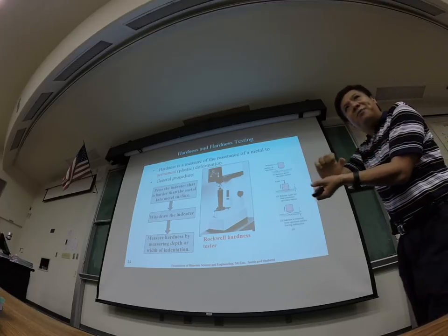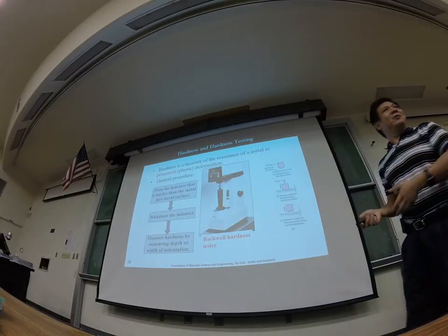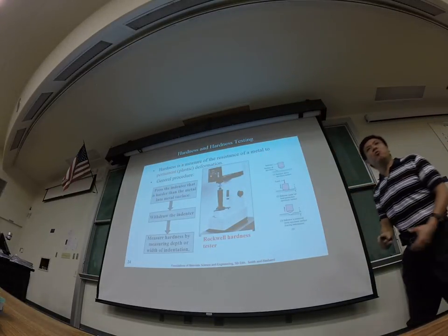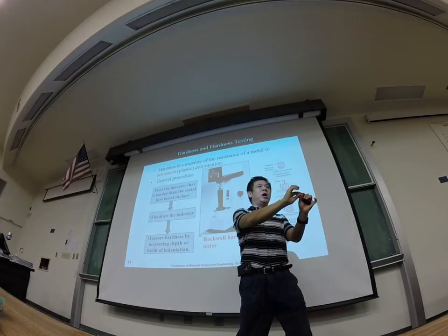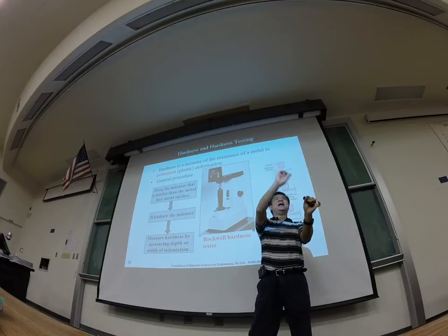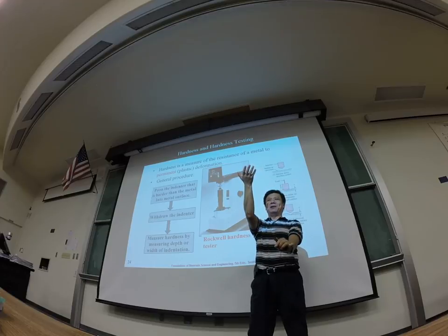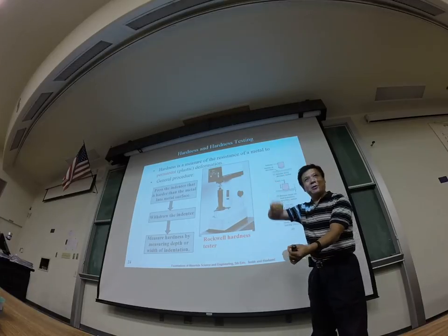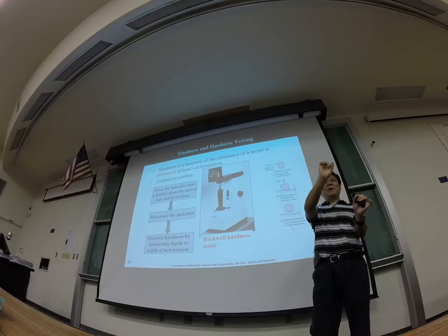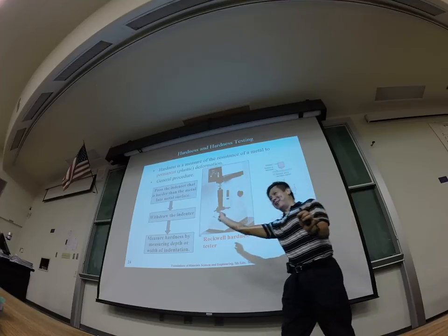When the load is enough, the tip will be pressed into the material. In this stage, we want to apply a load that is high enough. We don't want the material to stay in the elastic stage. Otherwise, when you release the tip, what will happen? It will spring back, and you won't see anything on the surface of the material. You want to apply a load that is high enough that it will go beyond this elastic range into the plastic range.